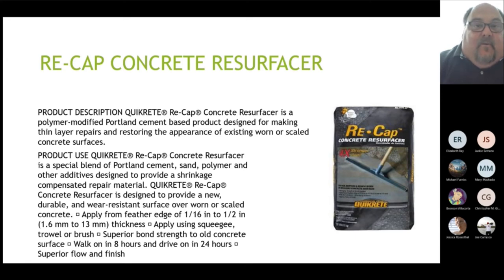Plus, it looks nice when you come home. It looks like brand new concrete. The product is really easy to use, believe it or not. The prep is going to be at least a 3,000 psi pressure washer. Make sure all the grease, dirt, and paint is out of there before you start using this product. If you do have to etch, make sure it's neutralized.